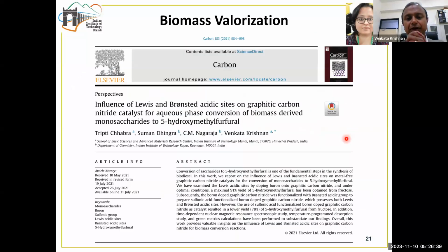As a follow-up of this work, we thought that if incorporating Bronsted acidic nature and Bronsted basic nature on the catalyst improves its catalytic properties, why not further introduce another, Lewis acidic nature? So there is a double acid nature, Lewis acidic nature and Bronsted acidic nature, on the same catalyst, and we wanted to see whether the reaction yield and conditions would improve. However, although we anticipated that the Lewis acidic nature and the Bronsted acidic nature would act synergistically, in reality, we found that they are acting antagonistically with each other.